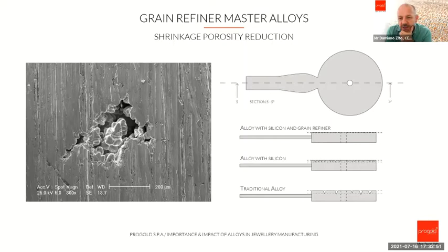Yeah, sure. Technically, the grain refiner is not reducing the volume of shrinkage, which is the difference between the volume of the alloy in liquid state and the volume of the alloy in solid state. The shrinkage will be in the range between 3.5 and 7%. We have equipment at ProGold to measure the shrinkage during solidification. But what is changing is that if you have many nucleation points,